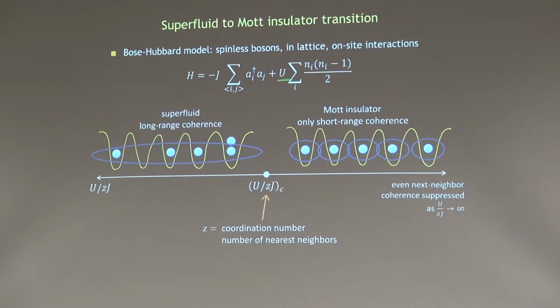And it's one that occurs in systems that are described by this Hamiltonian, which is the Bose-Hubbard Hamiltonian. It's one where there are particles that hop around in a lattice. So this basically describes band structure. And then the particles within a single site also interact repulsively with one another. And it's now sort of well known within this field that as you increase the strength of interactions, going from weak interactions to strong interactions, you transition a system from a superfluid phase where the atoms are delocalized and there's long-range phase coherence within the gas, to an insulator transition where the atoms are localized and where the coherence rapidly shrinks from having a coherence length as large as the system to finally having a coherence length that's just one or two sites depending on the depth of the lattice.